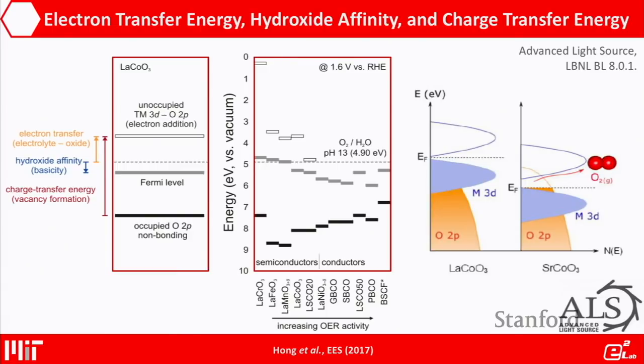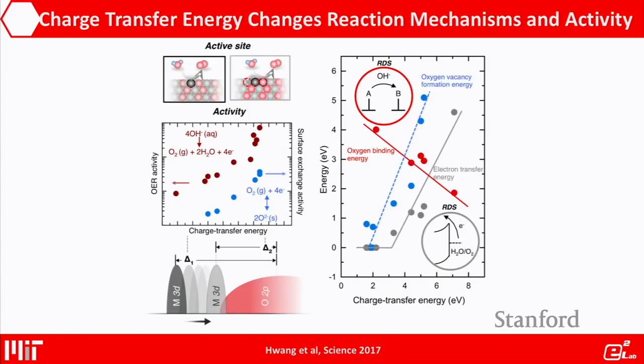Then you can align these energetics with the dashed line, the oxygen redox, and develop the barriers for electron transfer, hydroxylation, and charge transfer energy, which is critical to understanding the energy penalty to create oxygen vacancies on the surface. So armed with this information, we can develop the following understanding.